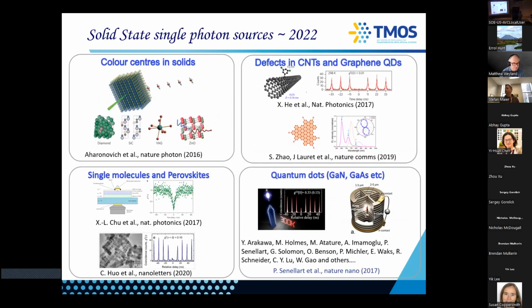Now, if you fast forward 15 years, the choice of single photon sources is quite large. So in reality, there are no problems anymore finding a single photon source. You just need to specify which wavelength you want and what material you want, and you will get one. And so there are a lot of defects in carbon nanotubes and single molecules, even perovskite crystals. Of course, the research into quantum dots really skyrocketed, and there are many, many groups. There is a beautiful review from Pascale Senellart, who is actually selling those sources now together with a cryostat. So if you want one at your home or on your desk, you can ask your supervisor to buy you one. It's a few $100,000, but you can get them on demand, emitting at about 900 nanometers.